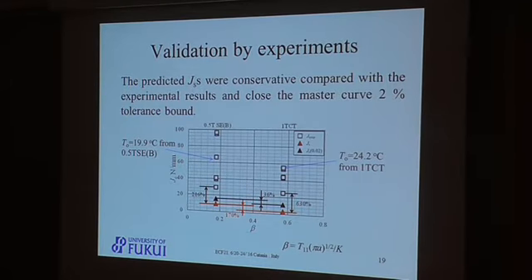Though there might be an opinion that the 2% tolerance bound values are still not the lower bound values in a strict sense, it seems that the predicted JSs give a good estimate of the lower bound JC in a practical sense. Thus, we concluded that the proposed framework has a possibility to transfer the lower bound JC between different specimen types and thicknesses in an engineering sense.